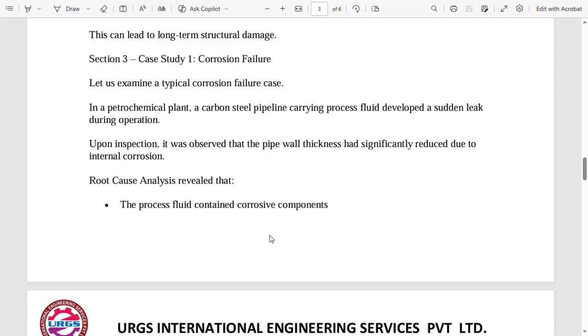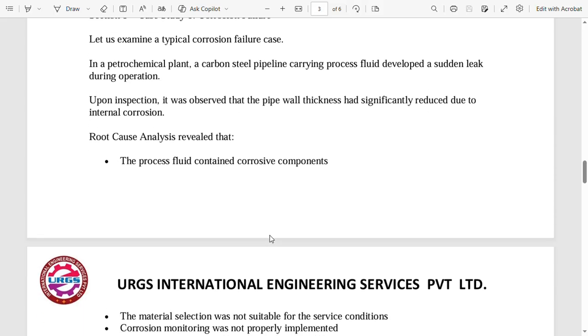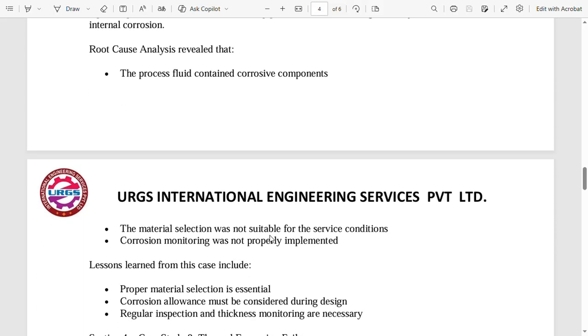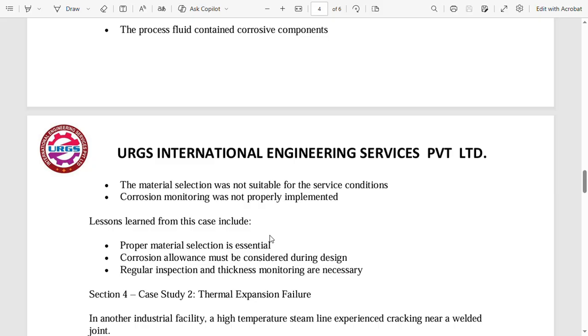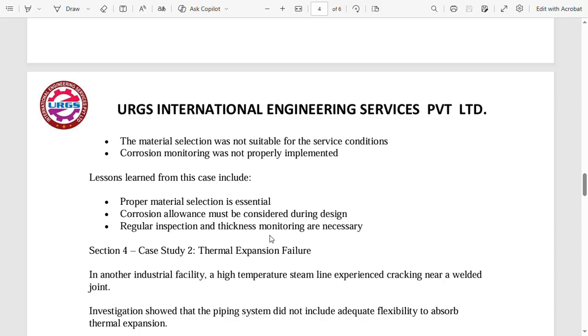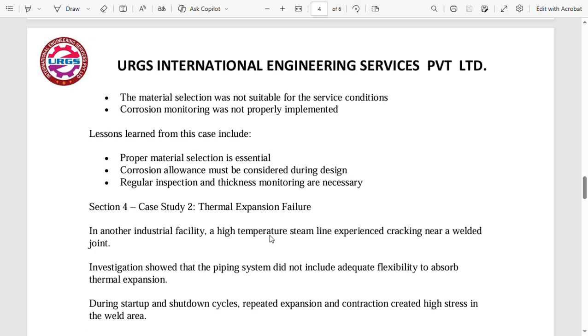Root cause analysis revealed that the process fluid contained corrosive components. The material selection was not suitable for the service conditions. Corrosion monitoring was not properly implemented. So what lessons were learned from this case? Proper material selection is essential. Corrosion allowance must be considered during design. Regular inspection and thickness monitoring are necessary.